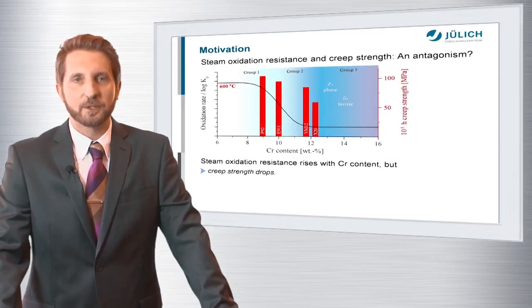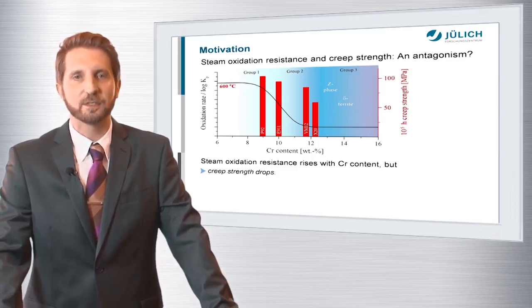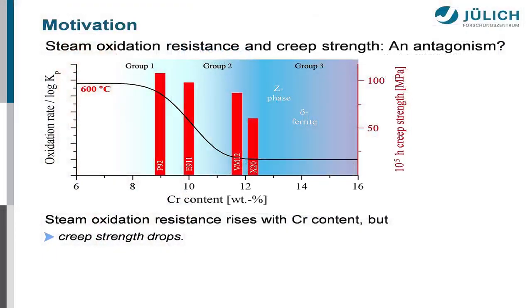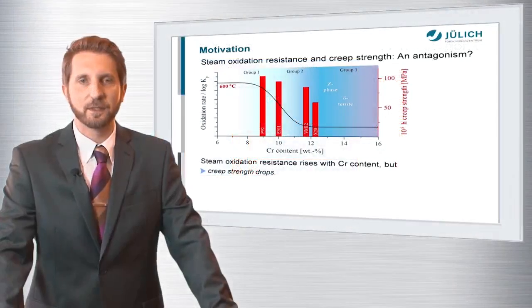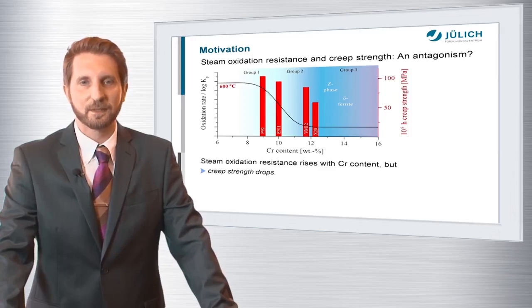So let me give you a short introduction on the steam oxidation and creep strength properties of state-of-the-art 9 to 12 chromium ferritic martensitic steels. You can see them here lined up as a function of their chromium content, starting out with P92 as a 9 chromium steel, going up with higher chromium content to VM12 and X20, which are 12 chromium steels. You can see the oxidation rate, which is represented by the black line, decreases with increasing chromium content. In turn, that means that steam oxidation resistance rises with rising chromium content. But unfortunately, on the other hand, what is represented by the red columns, the creep strength of these materials, the other way around, drops with rising chromium content.